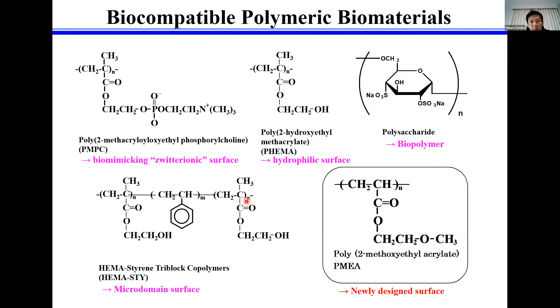This is a typical example of biocompatible polymeric materials. This is a biomimetic zwitterionic surface. You can see here a choline moiety with methacrylate. And here is a typical hydrophilic surface, 2-hydroxyethyl methacrylate, already used as soft contact lens material. This is a typical example of biopolymers, polysaccharide like heparin. And this is a block copolymer with varying OH groups — polyHEMA and styrene and polyHEMA — hydrophilic, hydrophobic, and hydrophilic.